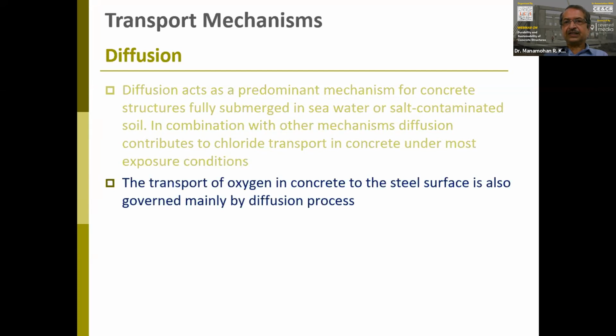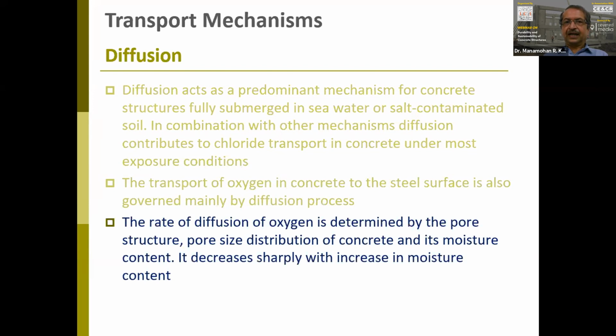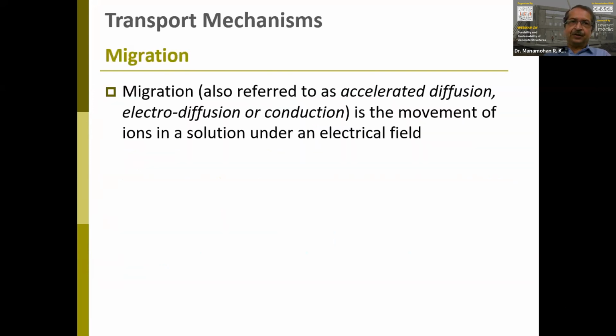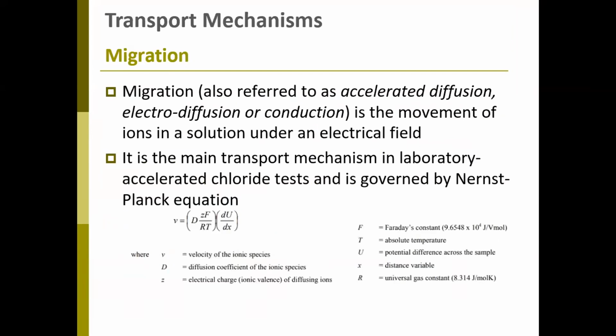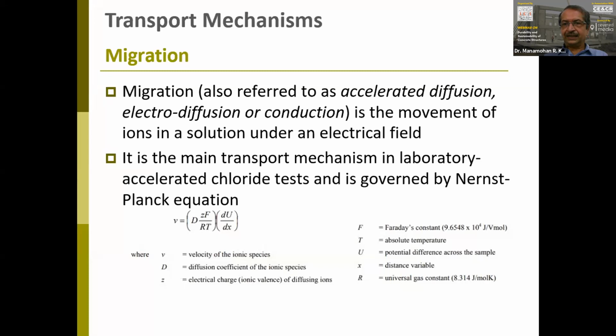The transport of oxygen in concrete to the steel surface is also governed by the diffusion process. The rate of diffusion is determined by the pore structure, pore size distribution, and its moisture content. So it decreases sharply with the increase in the moisture content. And when you talk of migration, which is also called accelerated diffusion or electrodiffusion or conduction, this is the movement of ions in a solution under electrical field. It's a main transport mechanism in laboratory accelerated chloride tests, and they are governed by this particular equation.